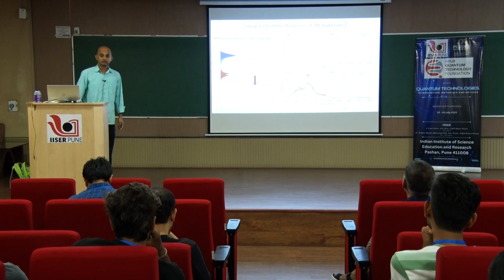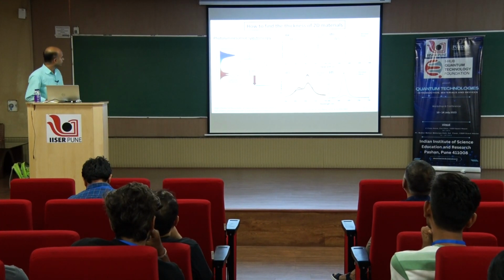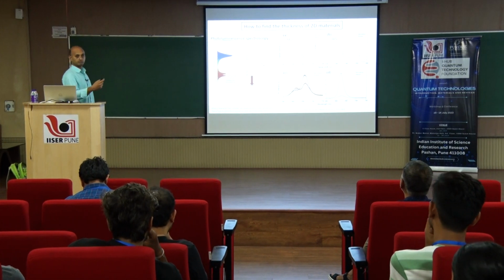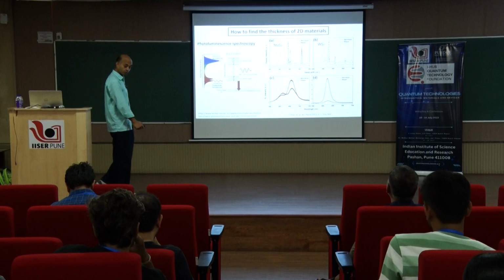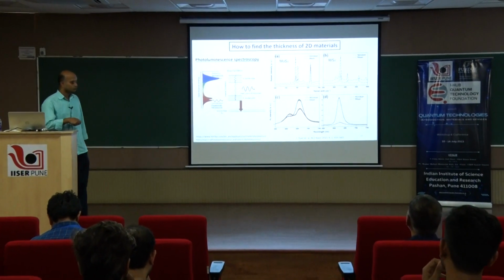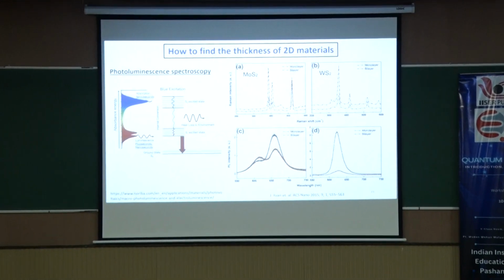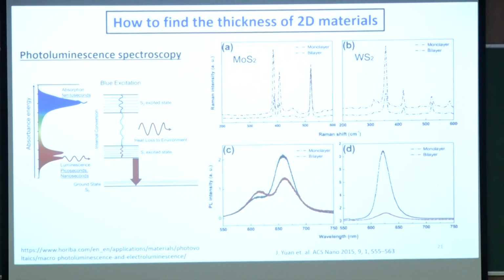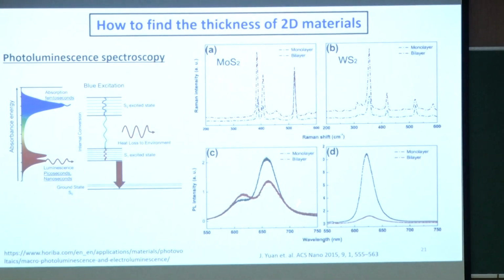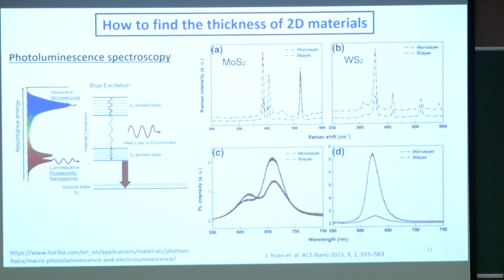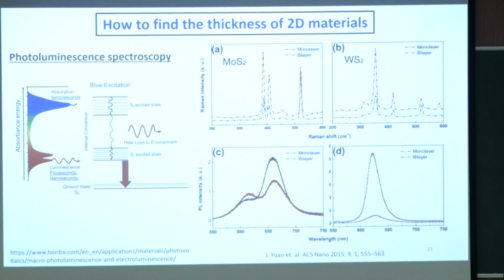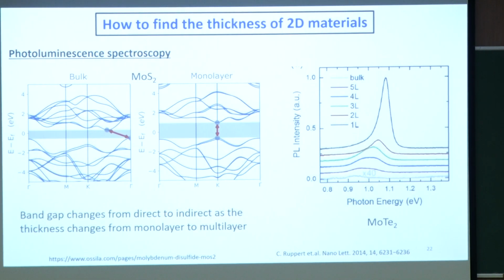Next is photoluminescence spectroscopy. This you can also use, but it is not useful for all monolayer 2D materials. Especially for TMDs, it is a very useful one, where you generally see a transition from indirect to direct band gap in the monolayer limit, because the PL enhances like anything. Here you can see that for monolayer and bilayer WS2, the PL is largely different. Here is again an example of MoS2. You can see how the PL changes drastically from one layer to bulk.